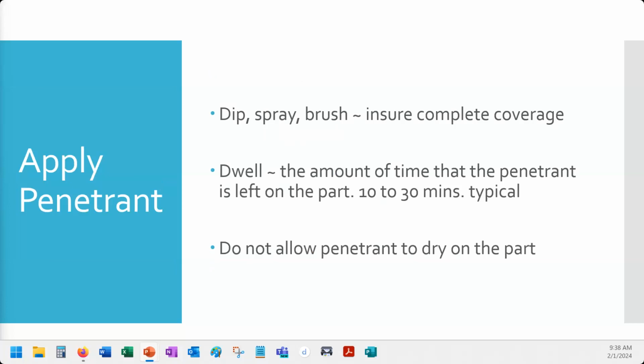Say we measured it last time at 1.5 inches, and this time we measured it at 1 inch. Cracks in metal do not self-heal. It did not shrink. What happened is it was not properly post-cleaned. It's on a turbine case that gets around 600-700 degrees, and it just baked that stuff in there.